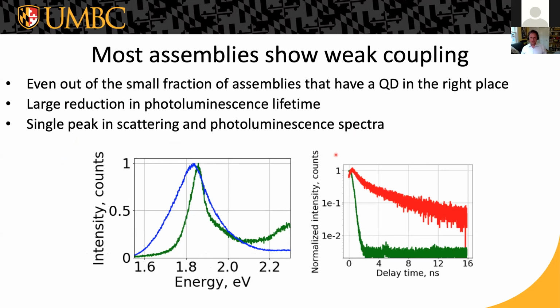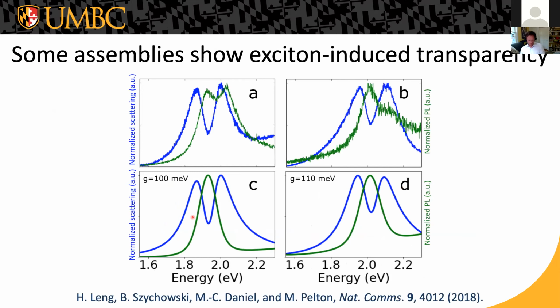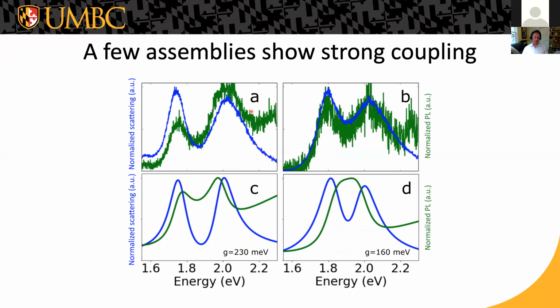So if a quantum dot's nearby the gap, we can still get a strong reduction in its lifetime, a strong Purcell enhancement, but the scattering spectrum here in blue and the photoluminescence spectrum here in green are largely unmodified compared to the spectra for the isolated particles. But every now and then, we're lucky, and there's a quantum dot in the right place, and we can get a strong modification of these spectra. So this is showing the example of the exciton induced transparency, the high cooperativity regime, where there's a pronounced dip in the scattering spectrum that coincides with a peak in the emission spectrum from the quantum dot. And if you have a patient graduate student who's willing to hunt around long enough, you will eventually find a few cases where you're really into the strong coupling regime, where there's a splitting of both the scattering and the photoluminescence spectra into the hybrid polaritonic modes.